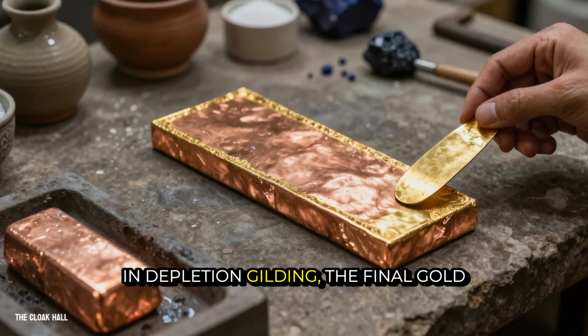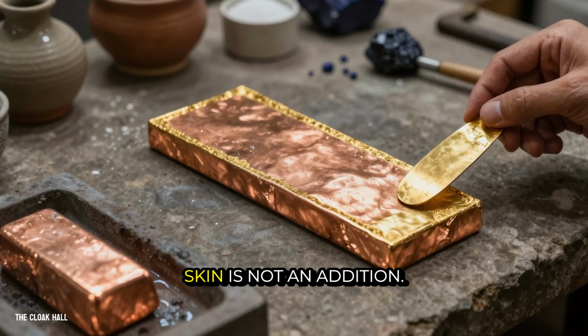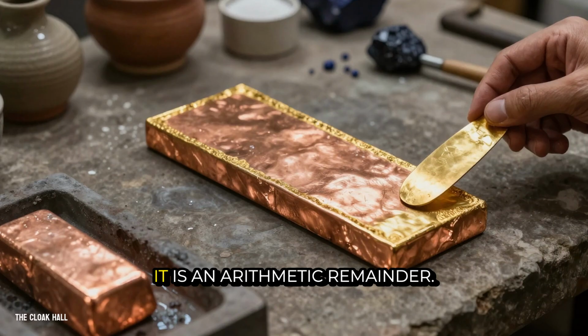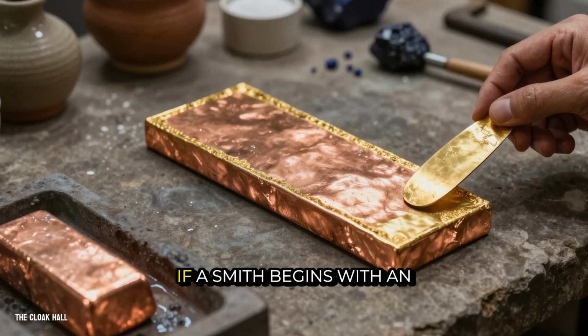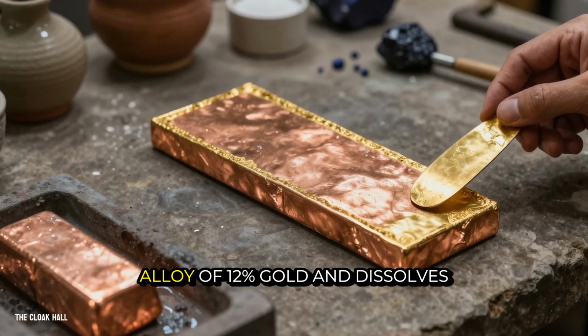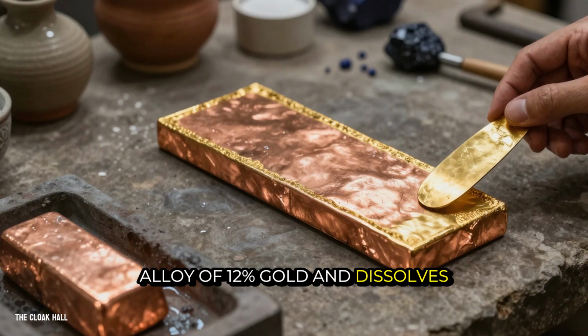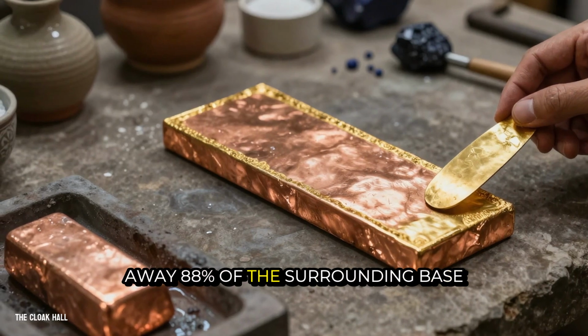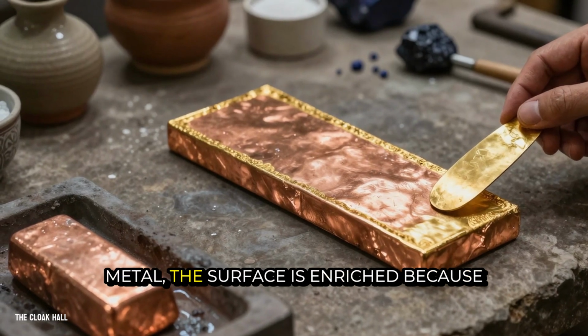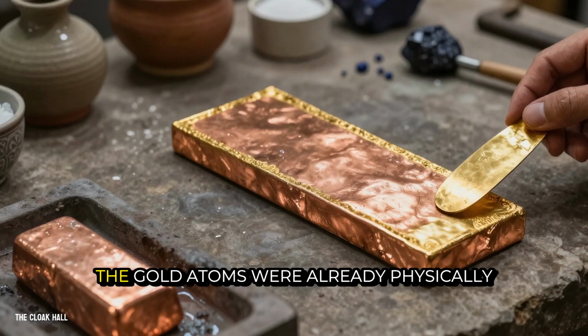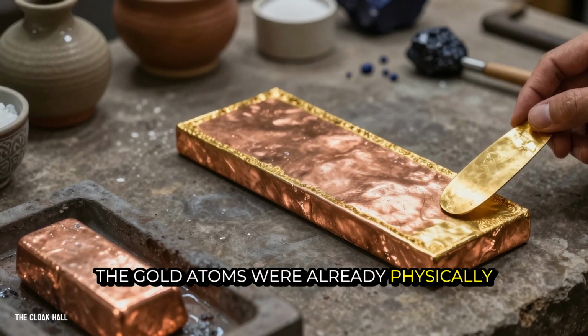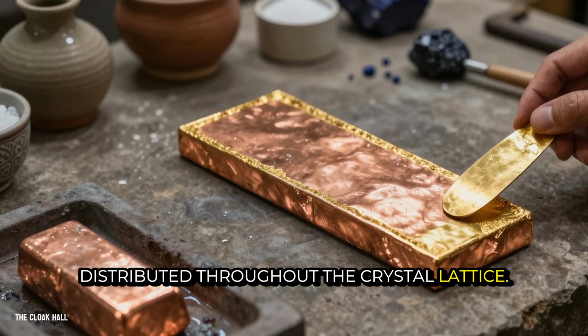In depletion gilding, the final gold skin is not an addition, it is an arithmetic remainder. If a smith begins with an alloy of 12% gold and dissolves away 88% of the surrounding base metal, the surface is enriched because the gold atoms were already physically distributed throughout the crystal lattice.